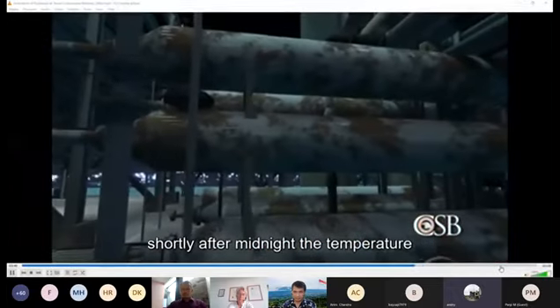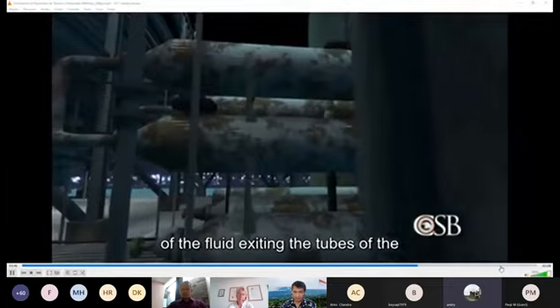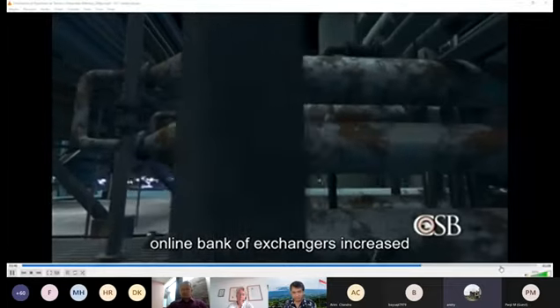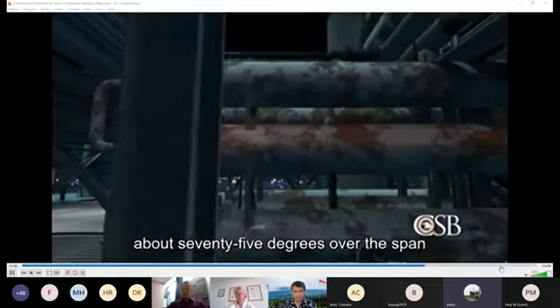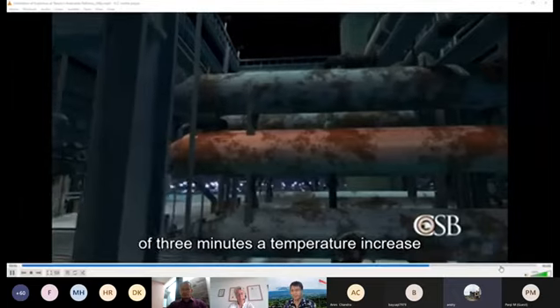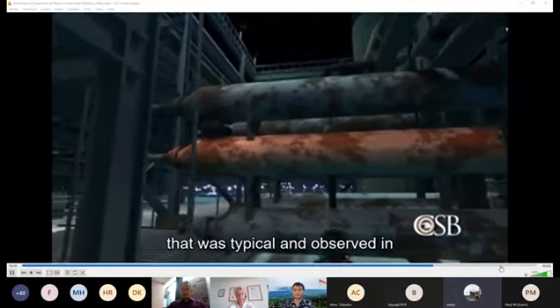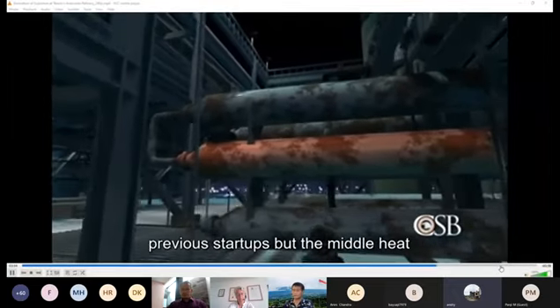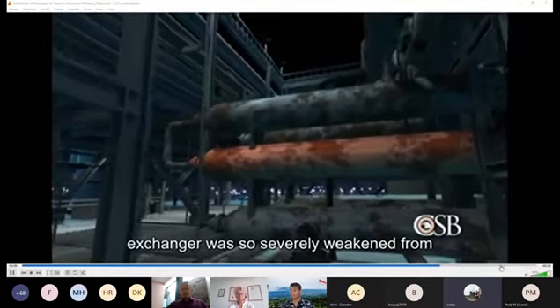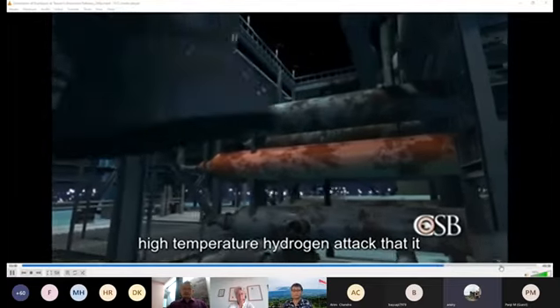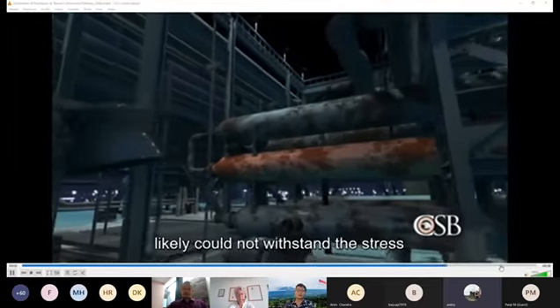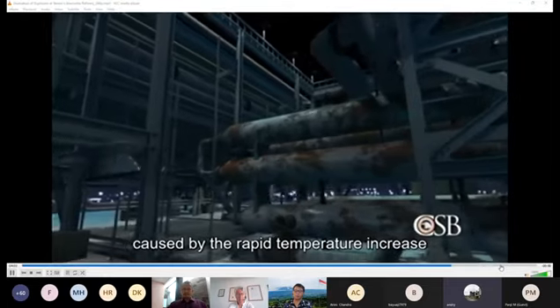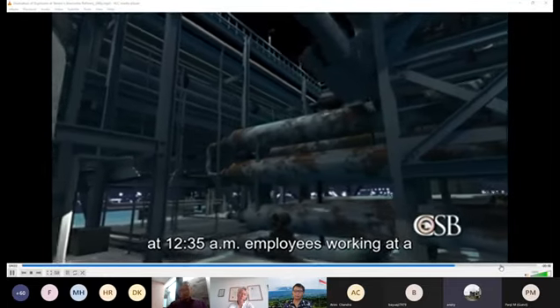One such crack was 48 inches long and extended more than 1/3 of the way through the vessel's 1-inch thick shell. Shortly after midnight, the temperature of the fluid exiting the tubes of the online bank of exchangers increased about 75 degrees over the span of 3 minutes, a temperature increase that was typical and observed in previous startups. But the middle heat exchanger was so severely weakened from high-temperature hydrogen attack that it likely could not withstand the stress caused by the rapid temperature increase.